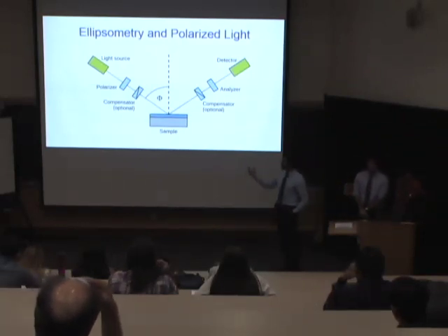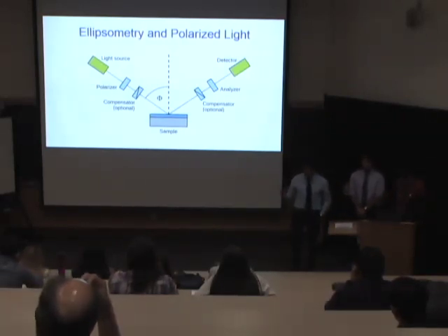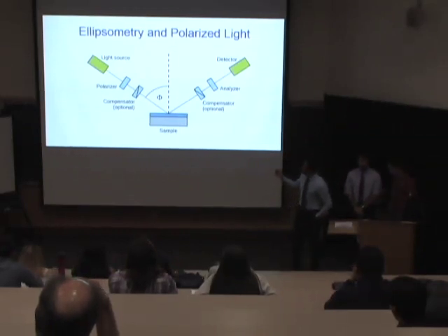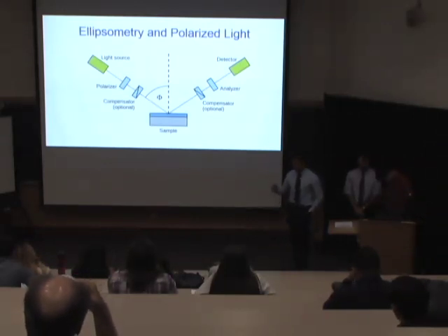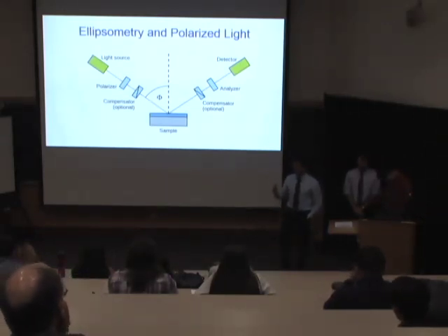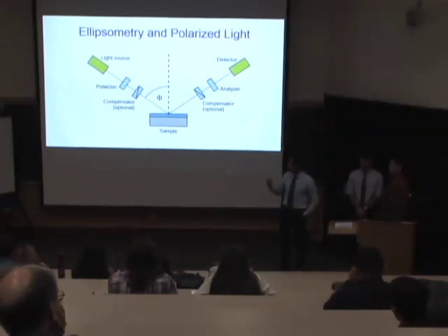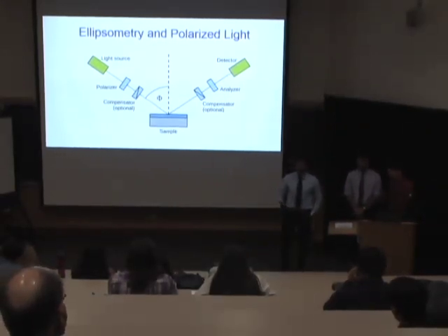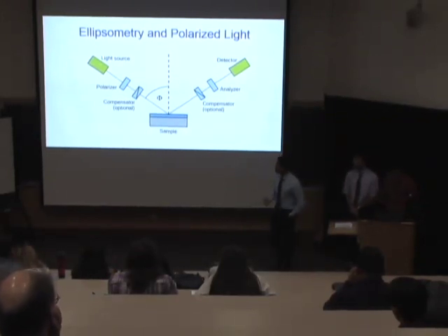The way it works, you have a light source and a polarizer. You have polarized light shining into the sample, and of course, you get a reflection out of it. The analyzer and the detector catch those changes, and the phase shift and the intensity will change. Just from getting our phase shift, we can determine properties like its roughness, its thickness, and optical properties, such as the index of refraction of our thin film.